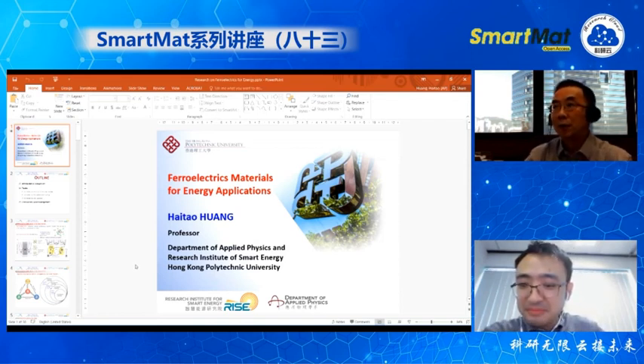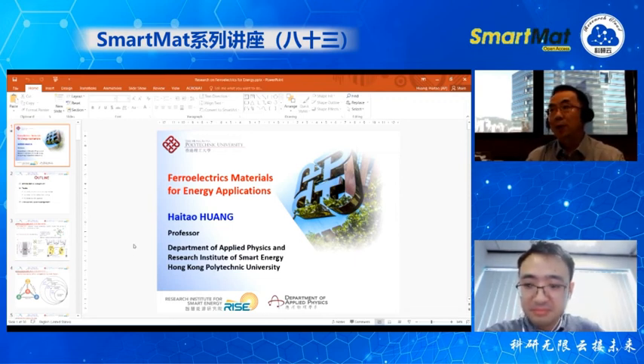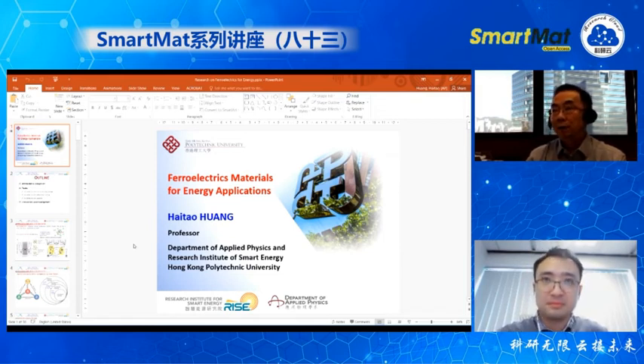Yeah, actually, we use different methods. For the parallel plate capacitor, we use the sputter method to deposit the film. And we have also used the pulsed laser deposition method to fabricate high quality thin films. And for electrocaloric cooling, we also use a similar method. It's just a film deposition method, using sputtering or pulsed laser deposition.